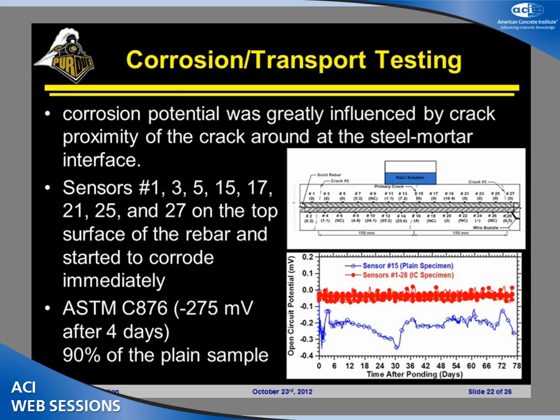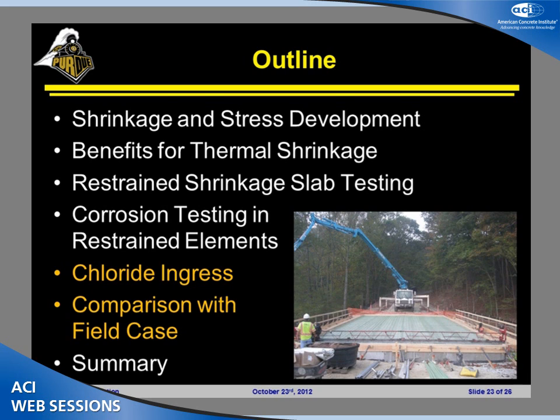The plain system, however, has that crack, and we can see that the sensors start to go into corrosion almost instantly. What's really intriguing about this, and what backs up some of the other work that we've been doing, is that it's not just corrosion taking place at the crack. We've got corrosion taking place substantial distances away from the crack surface, mainly because we're getting debonding in those areas as this crack forms. So the crack just doesn't go down to the bar and stop. The crack goes down to the bar, and we start to get debonding along the length of the bar, and that comprises a fairly substantial component of this.